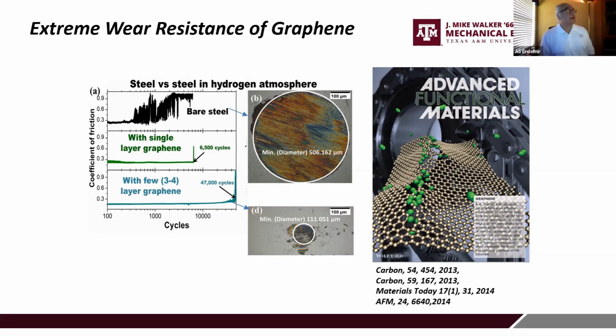Of course, these had to be done in a special environment, in this case a hydrogen environment. Hydrogen seems to stabilize the broken surfaces of graphene - under sliding contact you might eventually wear through or fracture the graphene cage, but these broken edges are neutralized by hydrogen so they don't further disintegrate or trigger stick-slip behavior causing high friction and high wear.